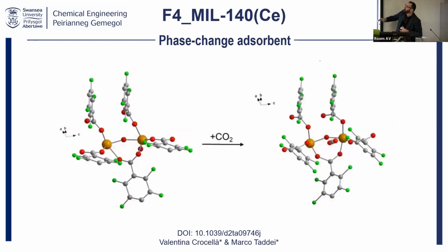And what happens? Now this even works. These two metals here are the metals with oxygen in between. And you might see those linkers now pointing towards it, intensely with the fluorine. When the CO2 comes in, a tiny flip like that, probably like 30 degrees, allows it to attract a CO2 molecule that you can see in the picture. What does this translate to? This concerted behavior of the linker